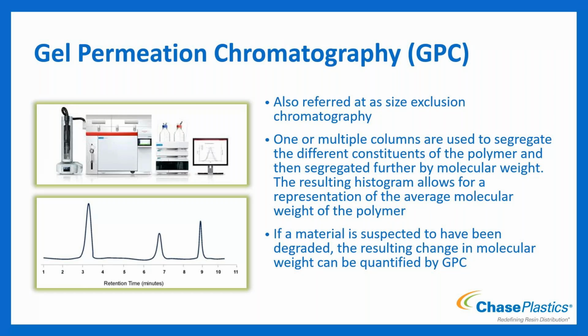So in the case where we're suspecting there might be degradation, so a lowering or an increasing of molecular weight, we can take the control, maybe pellets or a good part, and then compare it to one that we suspect there's been degradation, and compare the molecular weight. If the molecular weight lowered, maybe there was some hydrolysis or oxidation that occurred. If it increased, maybe there's some cross-linking. And so we can use GPC to look at that.